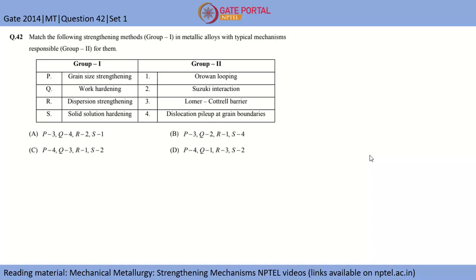In the strengthening mechanism NPTEL videos, you can find all these strengthenings, which are basically grain size strengthening, work hardening, dispersion strengthening, and solid solution hardening or strengthening. These are different types of strengthening, and precipitate hardening is also one of them. For every strengthening there are certain mechanisms for how strengthening occurs, and the main thing is that strengthening occurs because you are imparting things in the material which oppose the dislocation motion. If the dislocation motion is easy, then the material won't strengthen. Strengthening is basically requiring higher stress to deform a material.